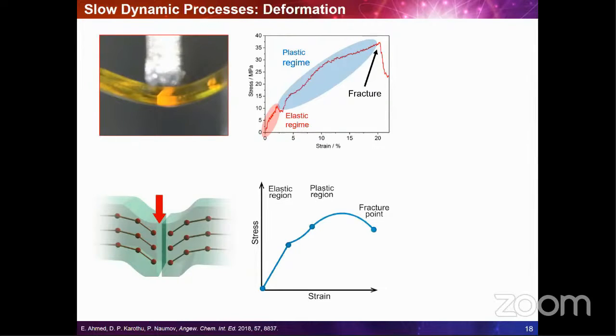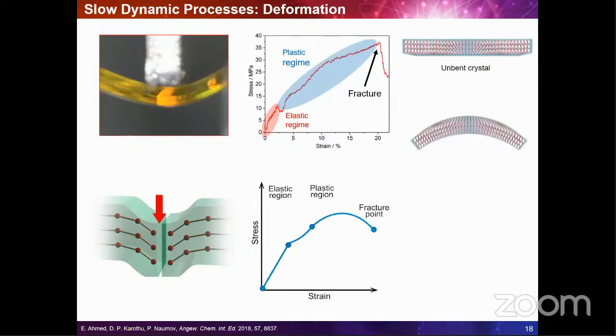After the applied stress displaces the molecules in the crystal and the stress is removed, the intermolecular forces will restore the original positions and the material will recover the original shape and size. However, once the upper limit of the elastic regime is reached, the material will undergo permanent or plastic deformation. And if it's stressed beyond the plastic region, it will yield and the crack will occur. So based on the difference in shapes and the limits of the stress-strain diagrams, the materials can be classified as brittle or ductile, or elastic or plastic. And now this is really a hot topic in solid state research where we're trying to estimate or predict the elasticity or brittleness of different crystals.